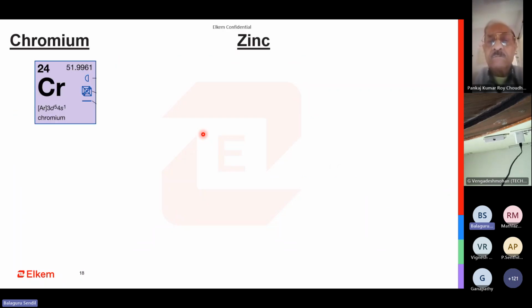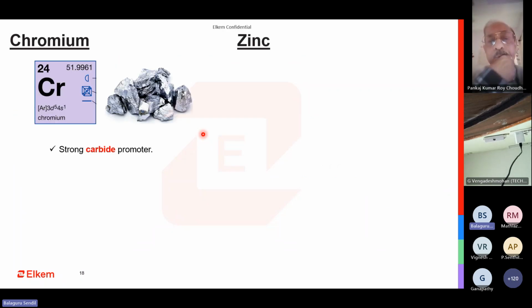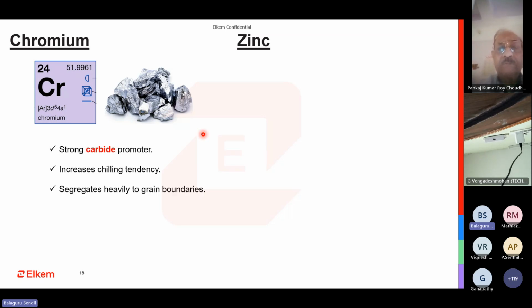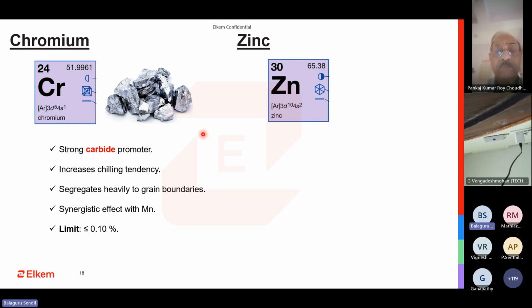Quickly on chromium and zinc. Chromium, we are all aware, is a very strong carbide promoter, which is going to play with the delta T. If you have high chromium, especially in ductile iron, you are going to run into the problem of high carbides. It also increases the chilling. It segregates to the grain boundaries very heavily, and this effect can be highly correlated to manganese, so the effect can be very similar. So chromium, we typically keep less than 0.1. We don't want to have more of that.